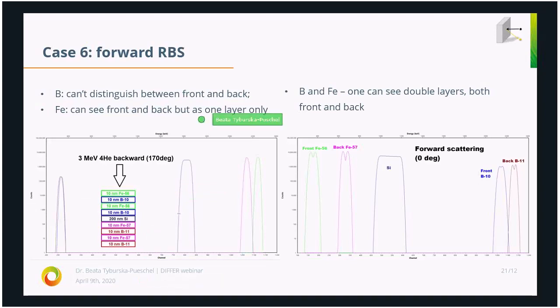And so here we have this sample we measured with RBS. And okay, you can see that we can distinguish between the top iron and bottom iron, but you don't see two layers. You just see one layer each for top and bottom. Then this signal is our middle silicon. And here we have signals from top and bottom boron, and they are overlapping. So when we use normal RBS for it, then generally we have a very poor depth resolution for those elements in our membrane.